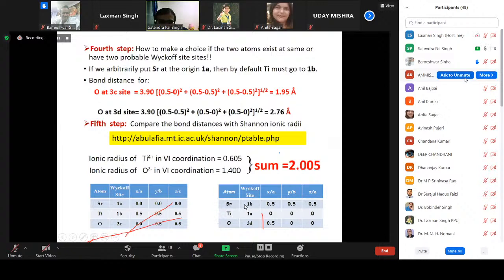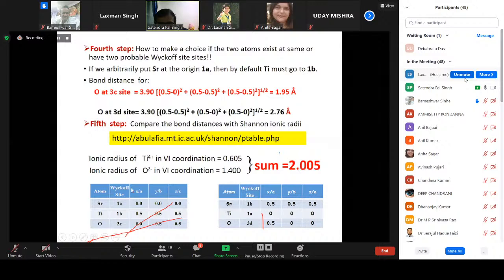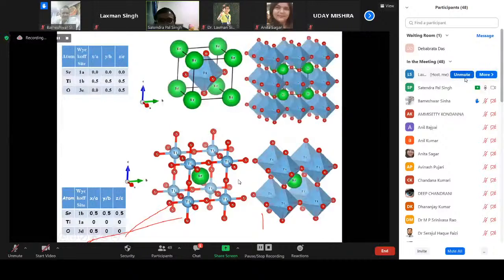In other cases, if you put strontium at the 1B site, that is also possible. Then titanium will automatically go to the 1A site, and the oxygen will go to the 3D site. Now, once you know all the occupancy positions in your crystal system, you will be able to generate these beautiful crystal structures.